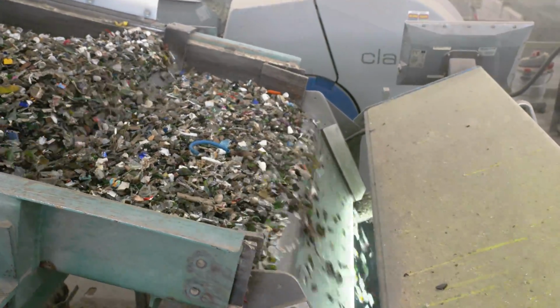So once the material has been through what we call the pre-processing line and the second set of cleaning and sizing, we bring it to the optical sort line. We use a series of optical sorters to remove additional contamination such as ceramic, stones, porcelain, or heavy plastics or other material we couldn't get out in the other cleaning lines. After we remove additional contamination, we start sorting by color. Once we sort the colors out into green, clear, and brown glass, or amber, flint, and green glass, it is moved to a finished product bunker where it's furnace ready and able to be sold to our end customer.